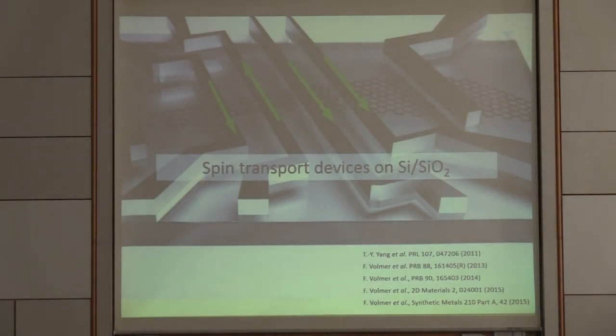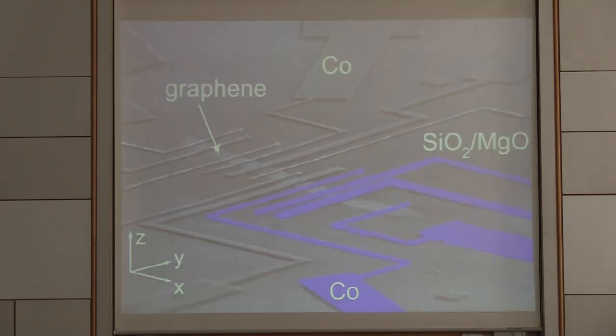Let me start with the prototypical setup of experiments which we use. I start with some older measurements on silicon oxide systems. So typical samples in early days looked the following way, that we have this silicon oxide substrate, then there is exfoliated graphene, and then there are ferromagnetic contacts which are separated by an MgO barrier.